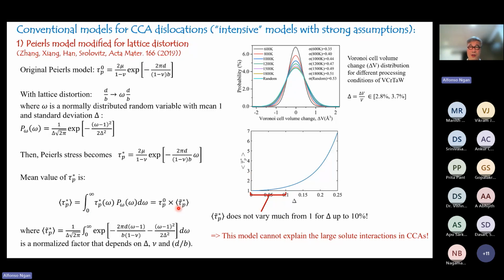However, as we calculated the exact value of this term, it turns out that this value is very, very small, as you can see, unless this delta, which is the lattice distortion, becomes really large. But in the usual range that we are talking about, 10% or below, you are talking about an increment due to lattice distortion of only 10%, 20%. So this is a very small contribution. Although the model is mathematically appealing, we do not think this is important. We have these very strong assumptions. So that's one of the intensive models existing in the literature.